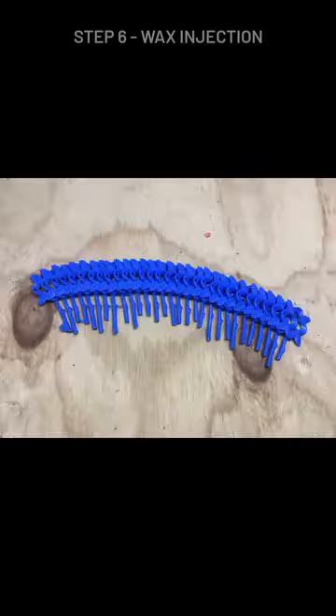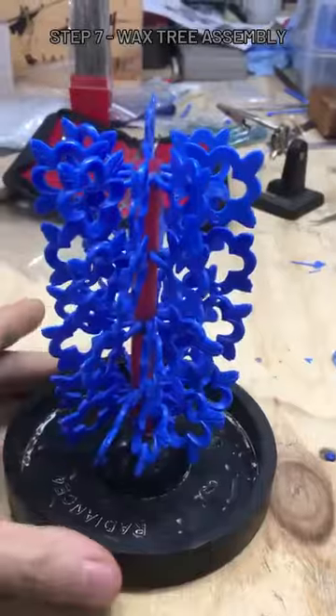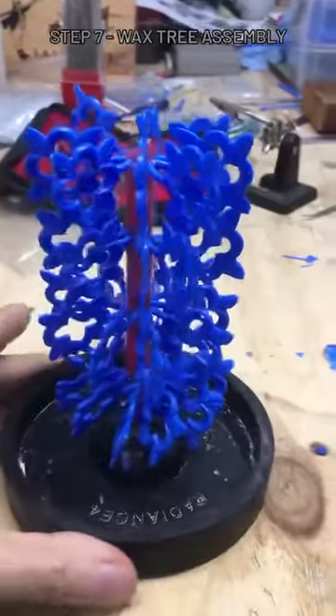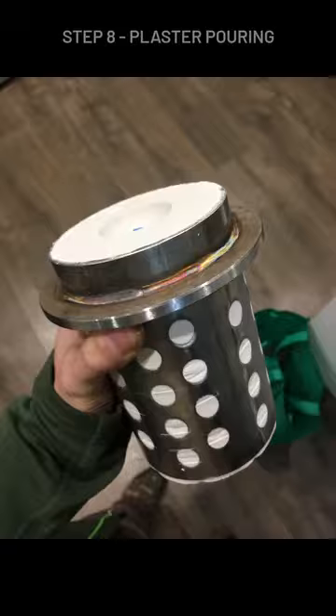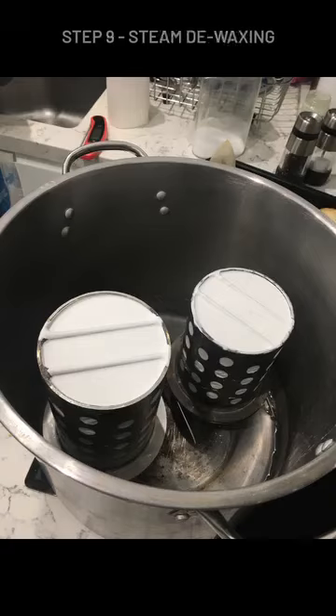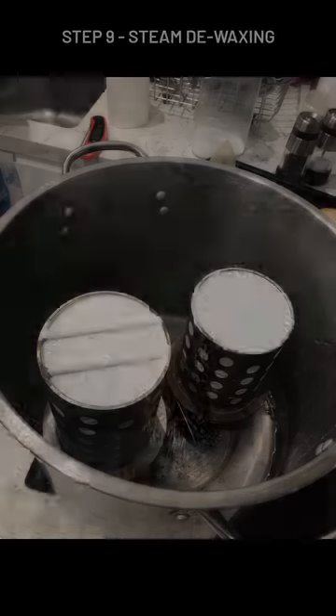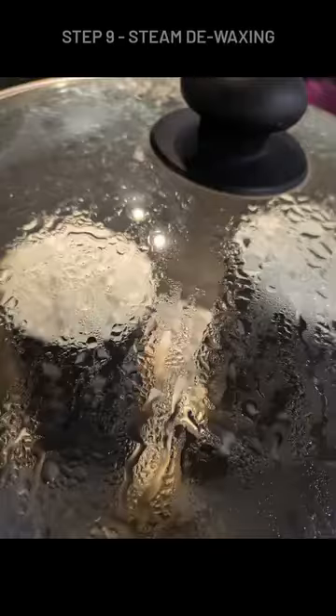Once we have a sufficient quantity of wax copies, they can be assembled into a tree, and this is placed inside the casting flask and encapsulated in the high temperature refractory plaster. Then it's into the steaming pot, and after a couple of hours of steaming, all of the wax is melted out, leaving a hollow void in the shape of our tree. The flasks then go into the kiln overnight, and they're gradually brought up to the casting temperature.